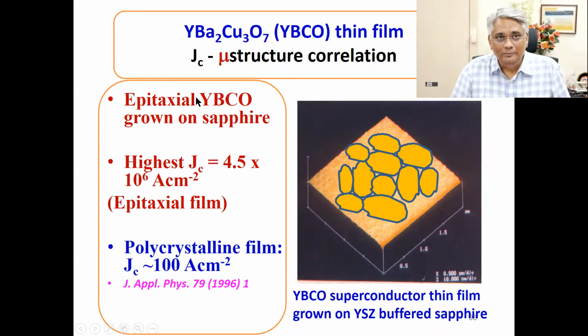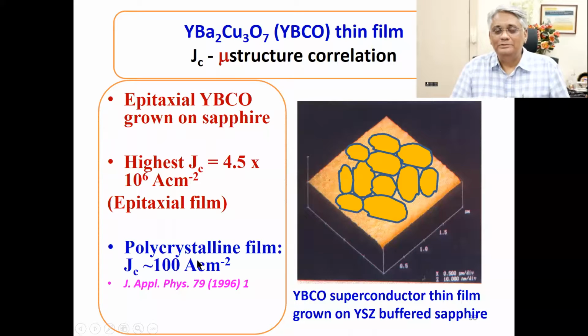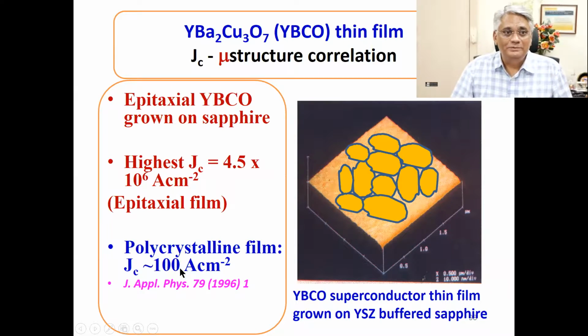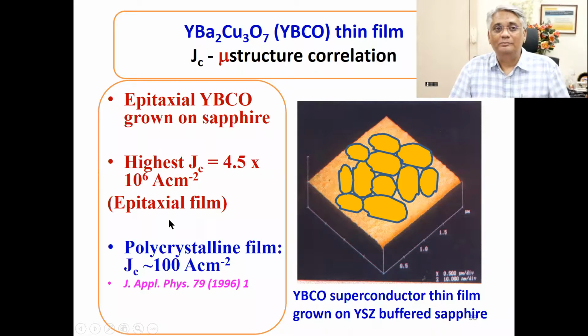And yttrium barium copper oxide being a ceramic that has grains and grain boundaries, you see, in a polycrystalline form, the polycrystalline system has grains and grain boundaries. The current density is hardly 100 amperes per centimeter square. Whereas the current density of a thin film is 10⁶ amperes per centimeter square, almost 4 orders of magnitude more.